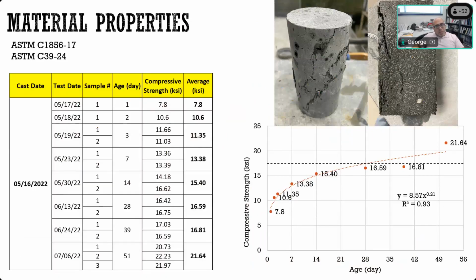Here's just showing you some of the properties that you get from this mix. These are results from a mix that was done actually not in the lab. This is not a lab mix where we do a small batch, but this is done at one of the precast producers in Nebraska. They did a large quantity, about 6 cubic yards of UHPC, and we did the testing for them back in 22. And you can see the compressive strength grow significantly, and even after 56 days, it's still going up, and we reach over 21,000 psi compressive strength, much higher than what you usually get from conventional concrete.